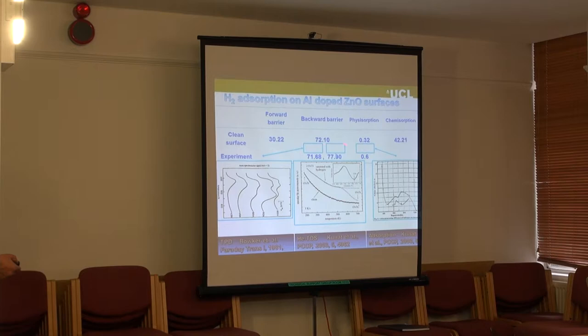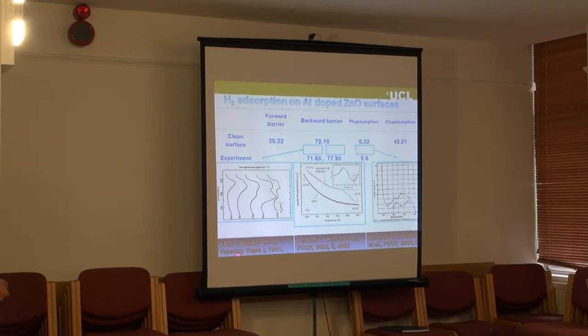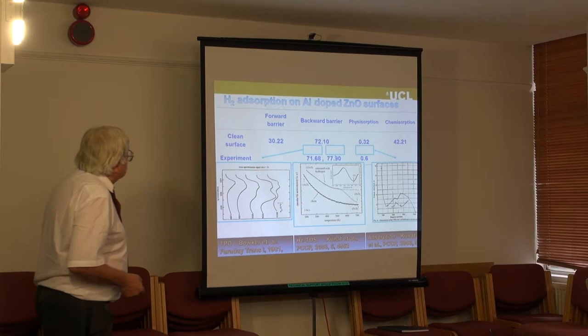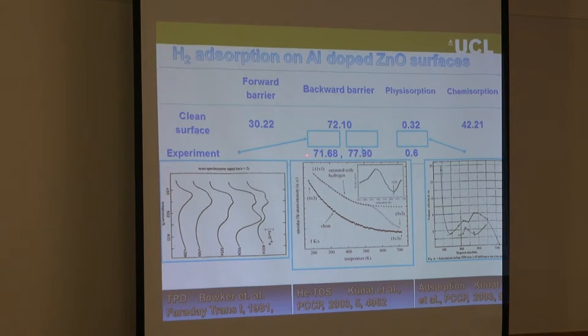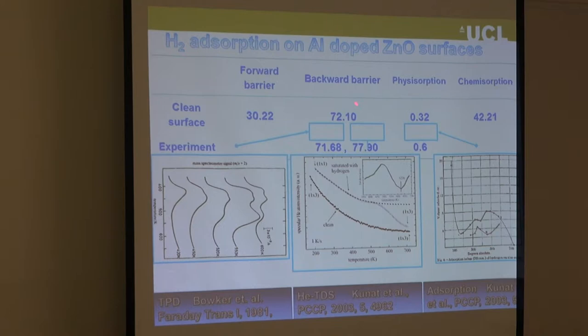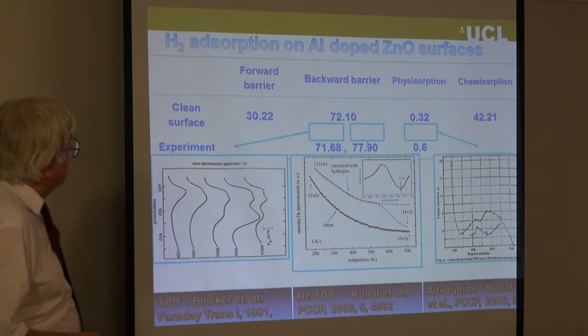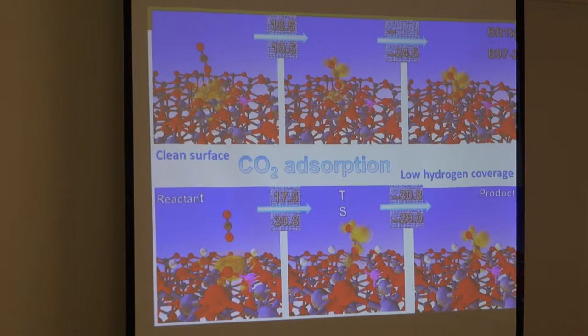Alexei was able to compare with experimental data, particularly very nice TPD data from Mike Bowker, formerly at ICI and now at Cardiff University. Comparing the desorption energy with the calculations shows really very good agreement, suggesting these embedded cluster calculations do a good job. Now let's look at CO2 adsorption. The spin density shows the electron trapped at the surface site, and when the CO2 molecule comes down, the electron transfers onto it to give CO2 minus — an active, non-linear species that can start picking up hydrogen atoms.